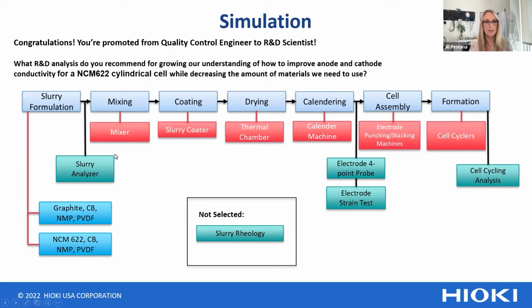The slurry analyzer point should be between mixing and coating. So my mistake. And then the strain test I would actually include, because this is a cylindrical cell, and so the electrodes have to be wound tight in a roll for that. And if we don't test for the strain, it could crumble. And so as we develop the electrode, we need to make sure it's flexible. So I would actually leave that in.